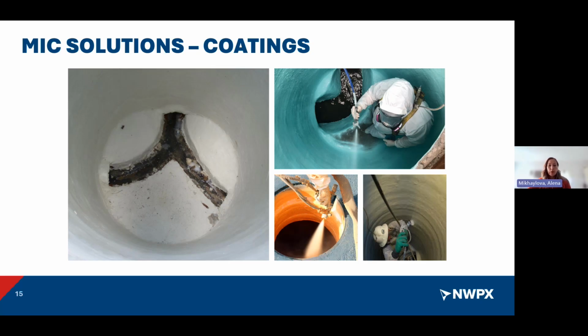The majority of these coatings fail because of cracking and adhesion issues. Gas gets in between the liner and the wall. It can create back pressure behind the liner, and these liners typically don't have, unlike CIPP, a fiberglass fabric. They don't have fiber inside. It's just epoxy or polyurea, which is very brittle. So if you have back pressure behind the liner, it can crack the actual liner. And once you have a crack, you can have gases going inside the crack, and it's going to start gradually eating up the concrete behind it and damaging the adhesion between the liner and the wall. So again, the average lifespan is 5 to 7 years.